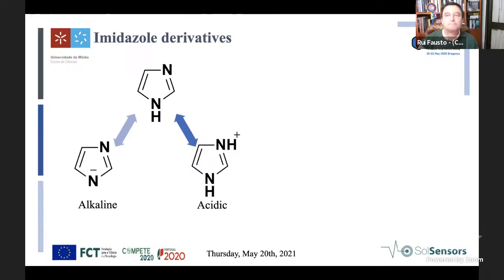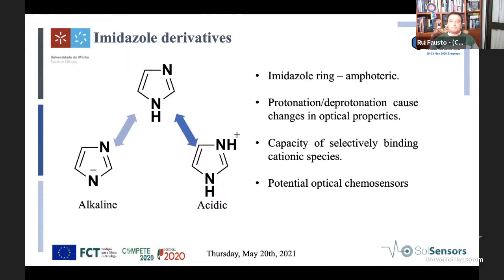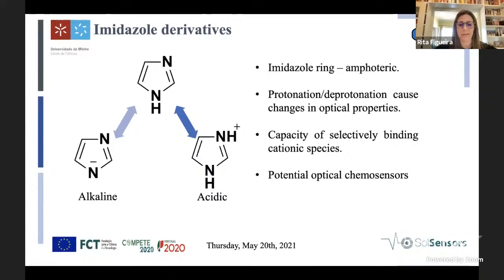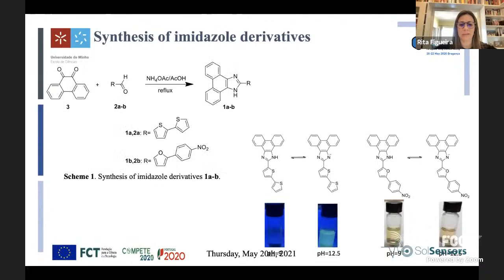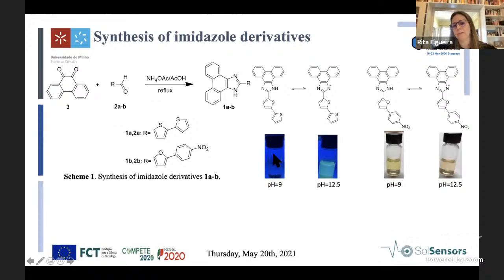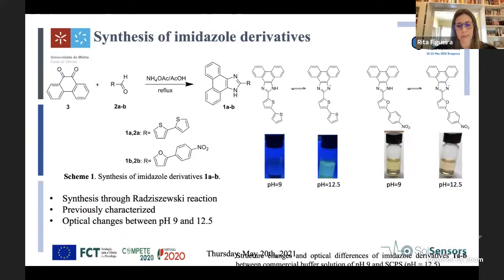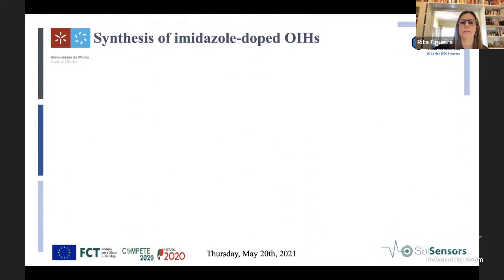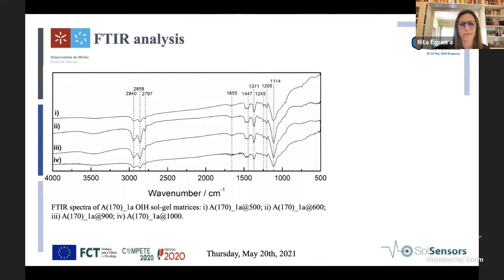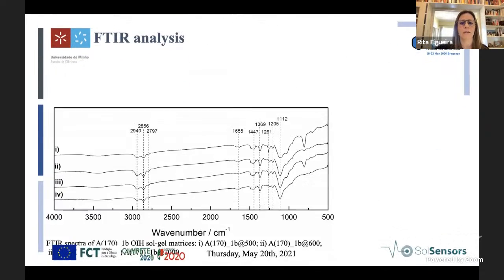And we tested some imidazole derivatives. This type of material is amphoteric, so you can see changes in optical properties, and they can act as chemosensors. I will show you these pictures. At pH 9, you see something like this. At pH 12.5, you see this. This is a fluorescent material. This is a colorimetric material. So we doped the same matrix with this, and we obtained stable matrices.